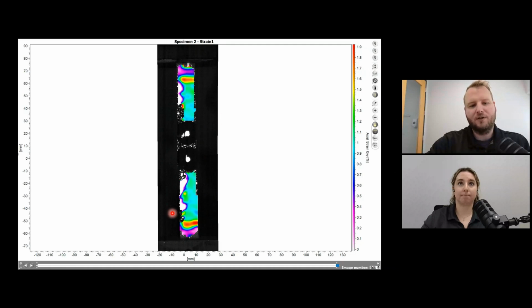Another quick thing here that was interesting was that one of the plies of the specimen seems to have delaminated towards the end of the test and actually came off. And you can see the software is no longer able to generate the strain field within that area. So depending on your failure mode, that might be something you need to keep in mind when you're running DIC on your specimens in your lab.